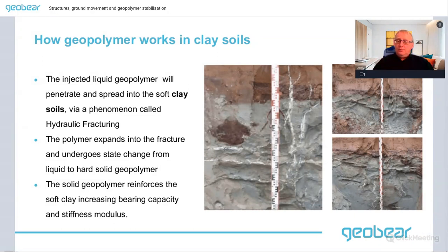So it's akin to putting rebar inside concrete to reinforce it. It adds a significant amount of stiffness to a soft clay, whereas the compressive strength of our polymers can run up to sort of 5 megapascals compressive strength, which is really quite high compared to the strength of a soft clay. So it's a reinforcing methodology of putting reinforcing into the clay to make it stronger.